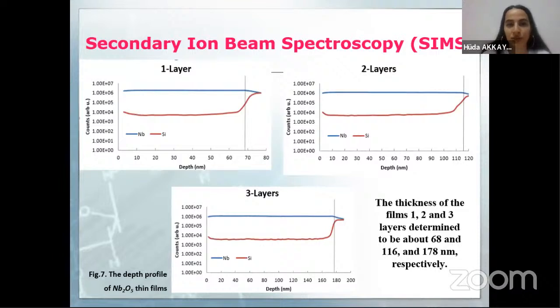And finally, secondary ion mass spectroscopy. Secondary ion mass spectroscopy is an elemental analysis technique that provides atomic homogeneity and surface characteristics with its depth in the ppm range. The secondary ions of niobium and silicon were detected using an oxygen gun, which sputters the flat surface and a crater is formed. The crater thicknesses were measured with a stylus profilometer, and from the SIMS analysis, niobium and silicon elements exhibited uniform and homogeneous characteristics.